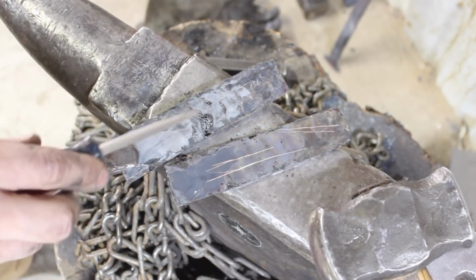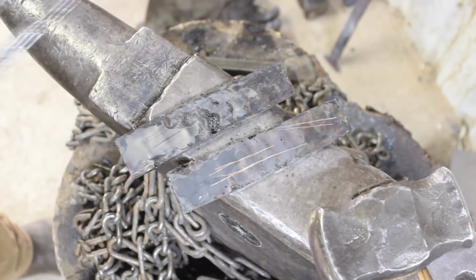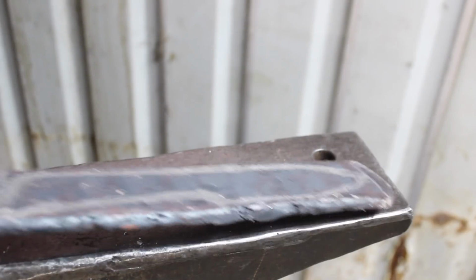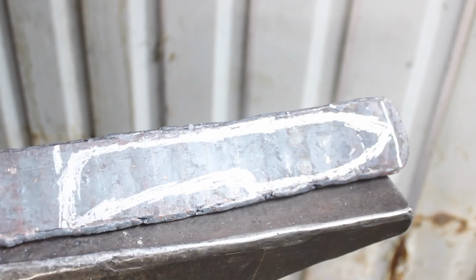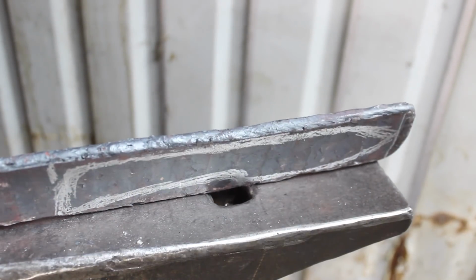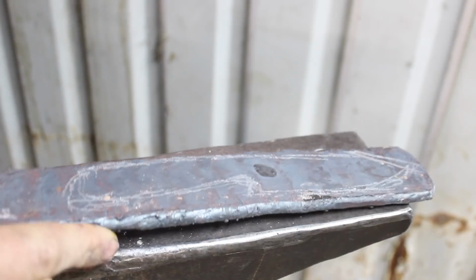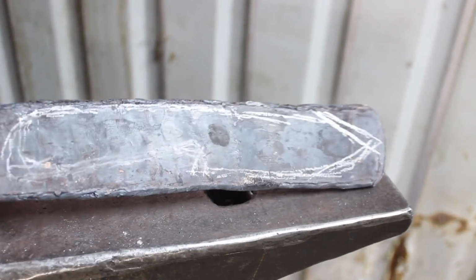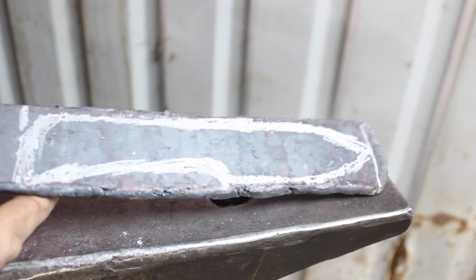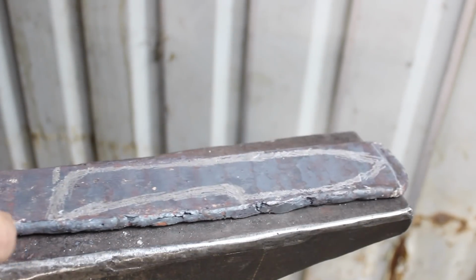So what I'm seeing is the copper, at the temperatures we were working it at, bonded pretty easily to the carbon steel, but not so much to the 52100. And I believe the reason for that is the chromium content in the 52100. Not that it couldn't bond to it, but it would need to be done at a higher temperature.